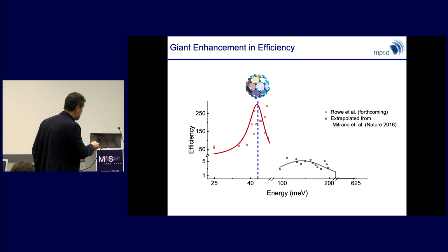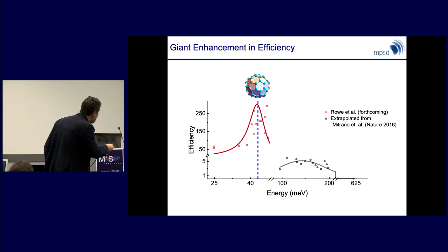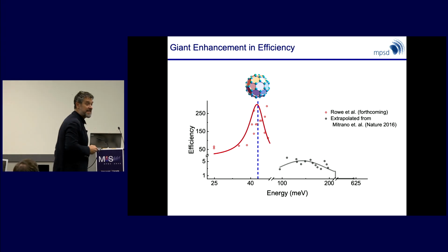And what he has found is an enhancement of 100-fold. This is where Matteo was pumping. And he has now found an effect that is 100 times more efficient when you pump at 45 meV, highlighting a dominant energy scale in the nonlinear response of this material.